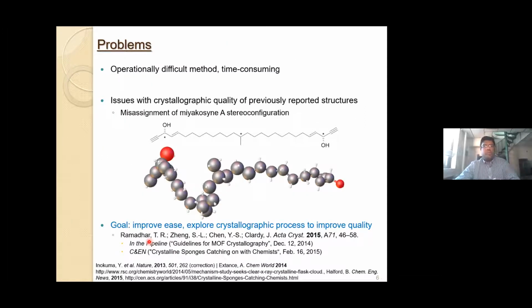So of course, when this paper was reported in 2013, there was a lot of excitement in the field, particularly from organic chemists and natural products chemists. They really wanted to try it out, and they did, and they ran into quite a few issues. So it is an operationally tough method to perform. The real tough part is not only including the compound, but actually growing the crystals and exchanging out the nitrobenzene for cyclohexane, because basically as soon as you try to do that step, the crystals basically all shatter.